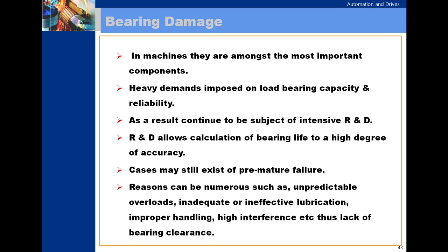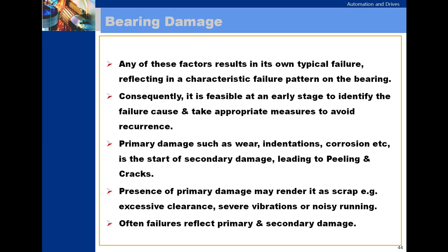Reasons can be numerous, such as unpredictable overloads, inadequate or ineffective lubrication, improper handling, high interference, or lack of bearing clearance. Any of these factors results in its own typical failure, reflecting in a characteristic failure pattern on the bearing. Consequently, it is feasible at an early stage to identify the failure cause and take appropriate measures to avoid recurrence. Primary damage such as wear, indentations, corrosion, etc. is the start of secondary damage leading to peeling and cracks.